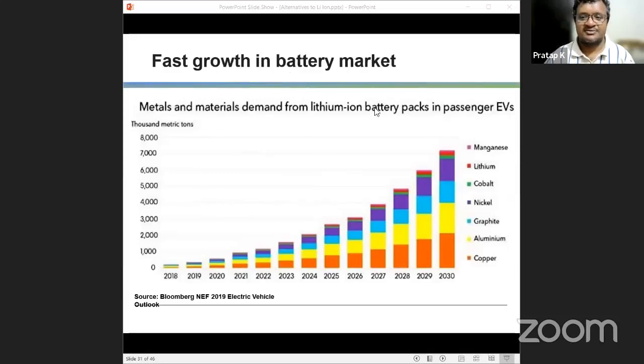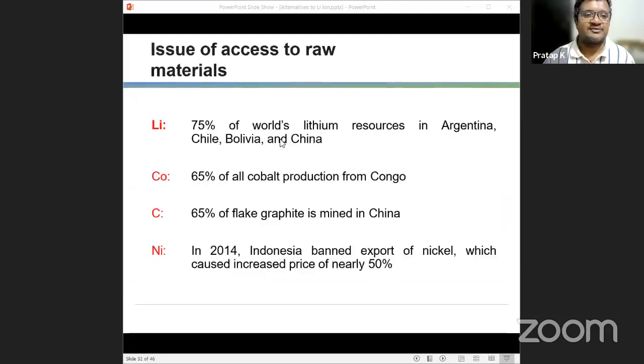When you look into lithium ion batteries, they don't come only with lithium. There are many other materials: copper, aluminum, graphite, nickel, cobalt, lithium, and manganese. These materials are also very expensive. This is what I'm saying, access to raw materials. 75% of lithium is in Argentina, Chile, Bolivia, and China. Cobalt, 65% of the cobalt is from Congo. Carbon, 65% of flake graphite is mined in China only.